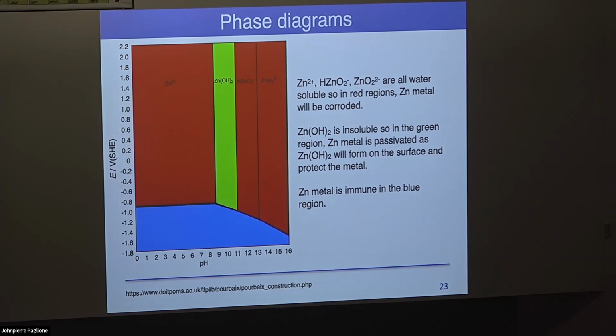In the blue region I mentioned before, it's zinc metal, completely unreacted, so that's what's called the immunity region. But in terms of the geochemical literature, something you might see as well is this green region, zinc hydroxide, which is what's called the passivation region. So zinc hydroxide is soluble in water, but it will form in solution. So if you put in a chunk of zinc metal, zinc hydroxide will form on the surface. The zinc hydroxide on the surface is not soluble in water, so your zinc metal piece that you put in will be passivated against further corrosion.